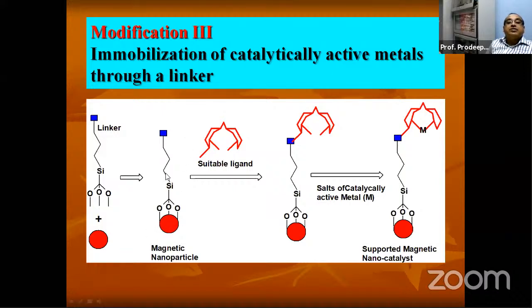So now this is a linker which got hooked onto the surface of the nanoparticle. Then you go for a suitable ligand, or if this linker has a very good functionalized end, we don't need another linker, otherwise you need some ligand. Then add the ligand, then you have this kind of structure, then a salt of the catalytically active metal, then here you could hook the catalytically active metals on the surface of the magnetic nanocatalyst.